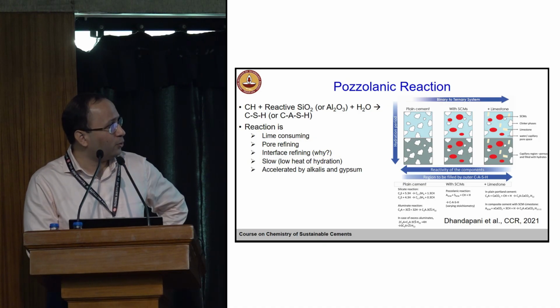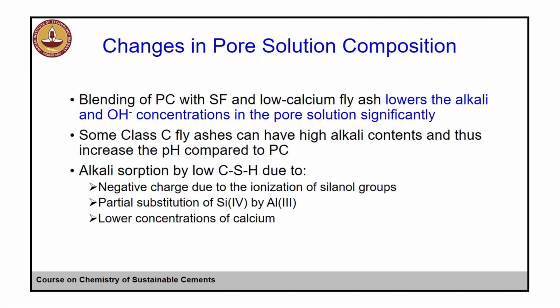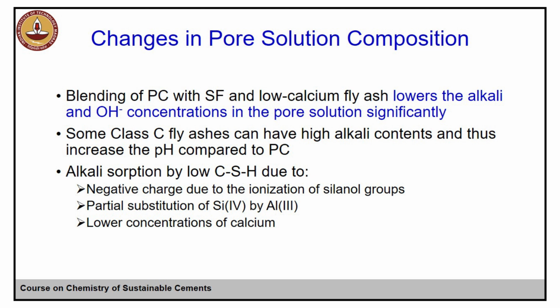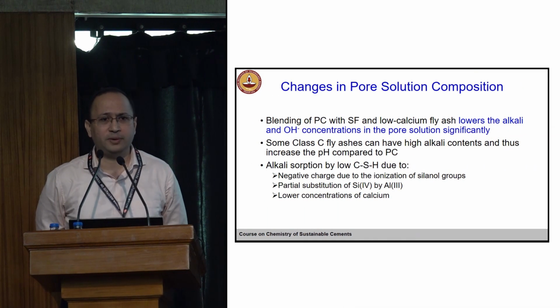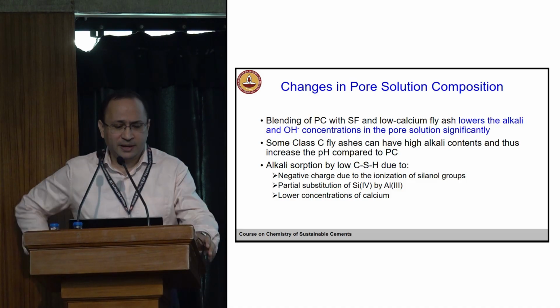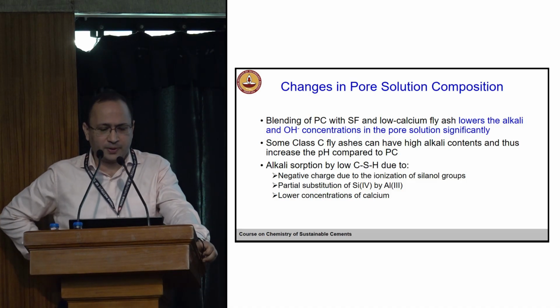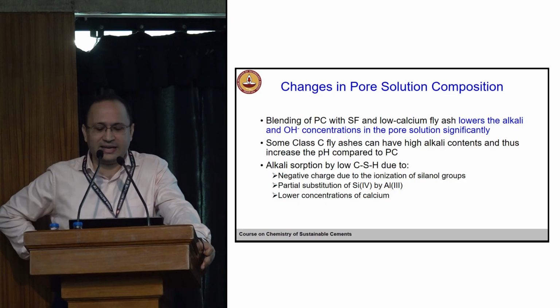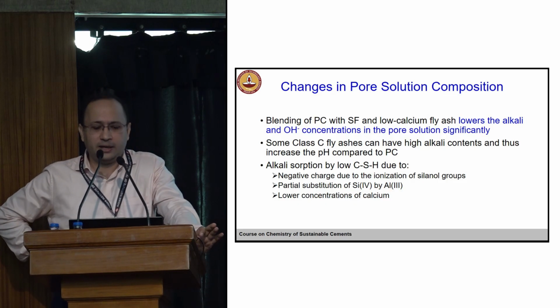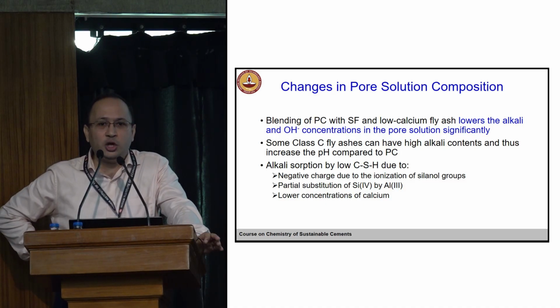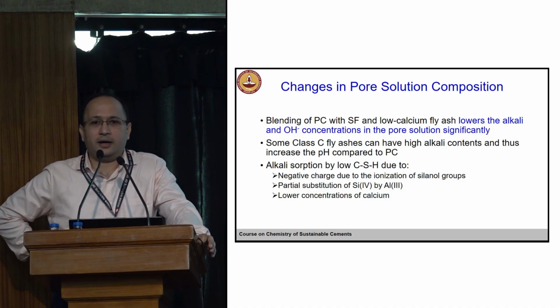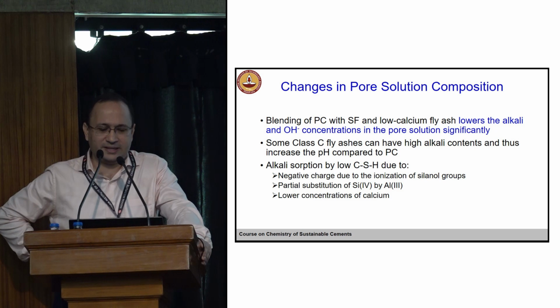You see refinement of the pores and overall improvement in the durability. As I said, pore solution composition changes drastically, and obviously it will depend on the type of SCM, whether it is fly ash, slag, silica fume, metakaolin, or calcined clay. Typically, when we blend Portland cement with silica fume or low calcium fly ash, it will lower the alkali content, and hydroxyl, like pH, will reduce. If you are able to extract the pore solution and measure the pH, you will see the reduction in the pH.